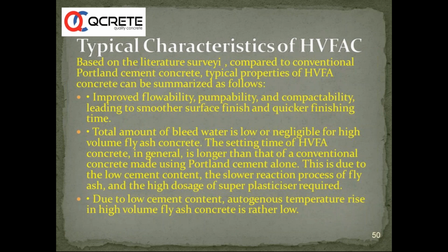So what are the characteristics? We have been repeating the usage and the benefits. Improved flowability, pumpability, compactability leading to smoother surface finish. Total amount of bleeding water is low or negligible in case of high volume fly ash concrete. Setting time of HVFA concrete in general is longer than the conventional concrete made using Portland cement alone. This is due to the low cement content, the slower reaction process of fly ash, and higher dosage of superplasticizer required. Due to low cement content, autogenous temperature rise in high volume fly ash concrete is rather low. So these are the characteristics of HVFAC.